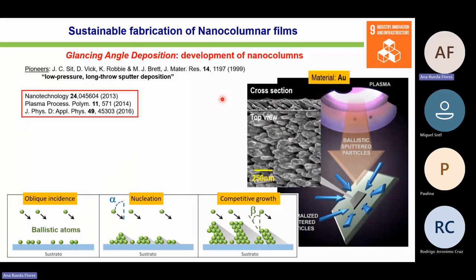So, as we have tilted the substrate, let's assume that all the atoms are ballistic, which means that they are traveling from the target to the substrate without suffering any collision. So the first atoms arrive randomly at the surface. The next atoms have a certain probability of being placed on top of some of the initial ones. And when they do that, they create a shadow region behind them that I have in gray. If all the atoms arrive with this direction, they cannot be placed in the shadow regions. So a competitive growth takes place. Finally, let's say that the small mounds fall in the shadow of the bigger pillars and they stop growing. So that's why at the end, if you have a look at the cross section, you have at the beginning some small pillars, but at the end, all of them have the same length, because the smaller ones stop growing. So this is the self-atomic shadowing mechanism.